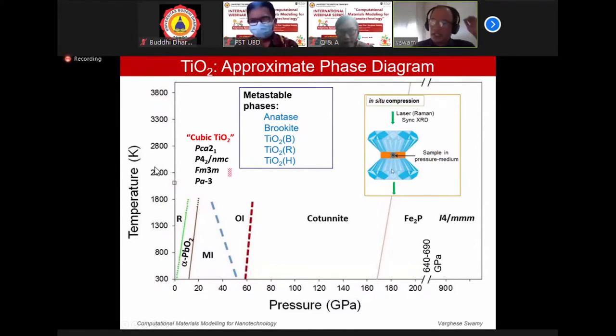And you stuff in the sample there and put some pressure transmitting medium so that you have a hydrostatic pressure, like what you experience when you go inside a swimming pool, that type of pressure, equal pressure all around you. And then you squeeze these two diamonds from opposite ends, and then through the diamond, you can send in X-rays at synchrotrons and collect the data and see what structure you get out of it. That's the experiment typically done to study pressure-temperature phase diagrams.